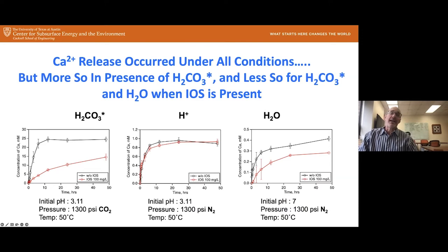So we took our calcite and put it in that high temperature and pressure reactor, and we did it for the three different experimental conditions, first without the anionic surfactant, the IOS, and then with it. When we look at just the black profiles, the ones without IOS present, the plot is over time, going for about 50 hours, and this is the concentration of calcium. We see that the calcium concentration is a lot higher with carbonic acid than with the proton or the water, so the carbonic acid is really driving the dissolution. We also see that when the IOS is present, it inhibited the dissolution of this calcite with carbonic acid and with water, but not measurably with the proton.